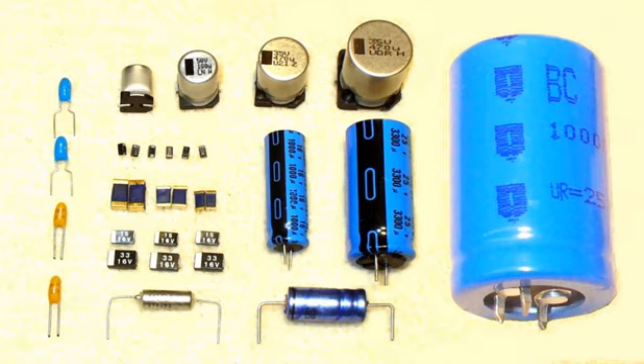Tantalum capacitors are now very reliable components. Continuous improvement in tantalum powder and capacitor technologies have resulted in a significant reduction in the amount of impurities which formerly caused most field crystallization failures. Commercially available industrially produced tantalum capacitors now have reached as standard products the high MIL standard C level, which is 0.01%/1000 h at 85 degrees Celsius and UR, or 1 failure per 10^7 hours at 85 degrees Celsius and UR. Recalculated in FIT with the acceleration factors coming from MIL-HDBK-217F at 40 degrees Celsius and 0.5 UR is the failure rate. For a 100 microfarads, 25 volts tantalum chip capacitor used with a series resistance of 0.1 ohms, the failure rate